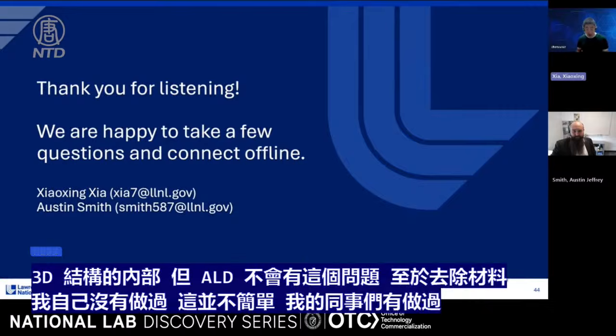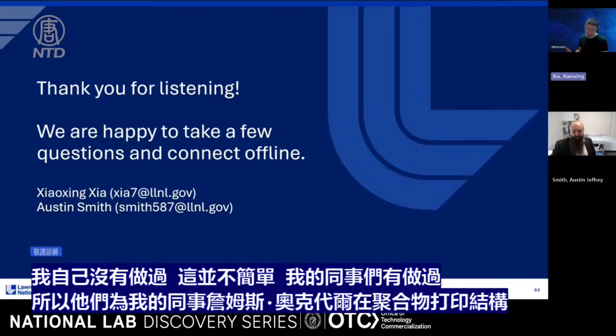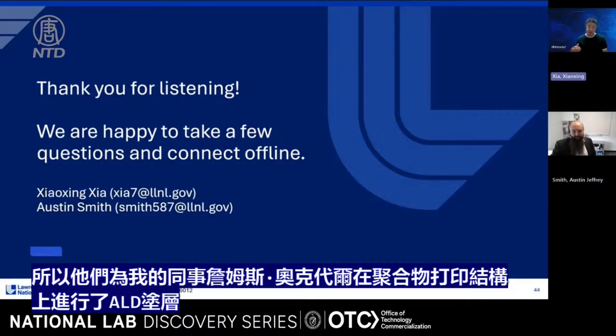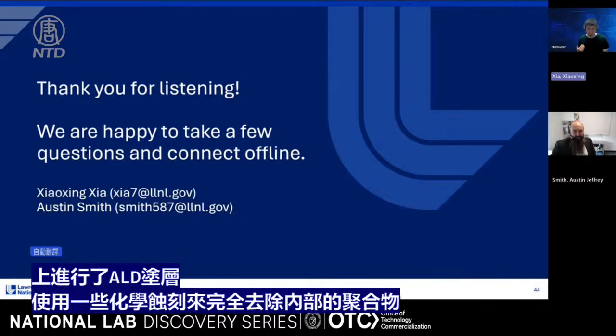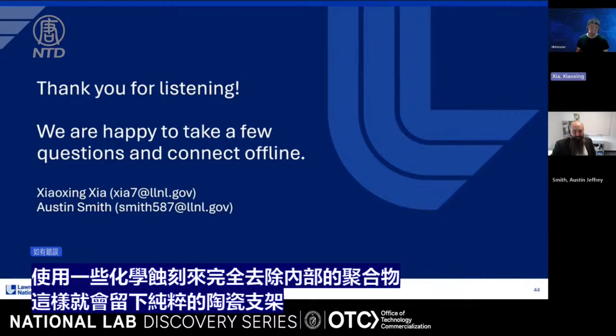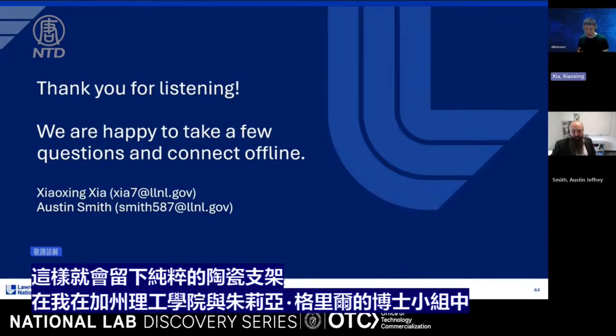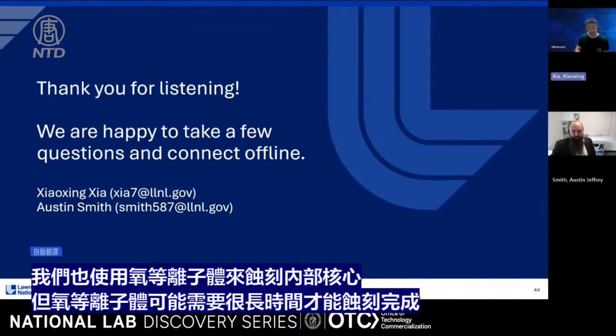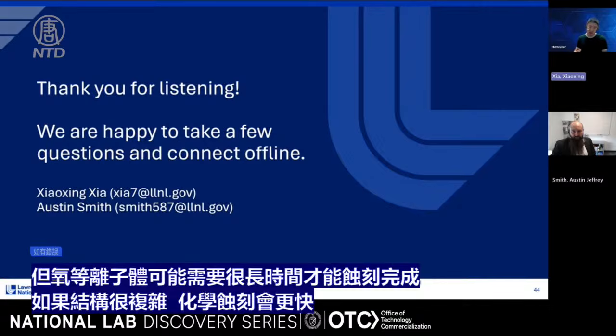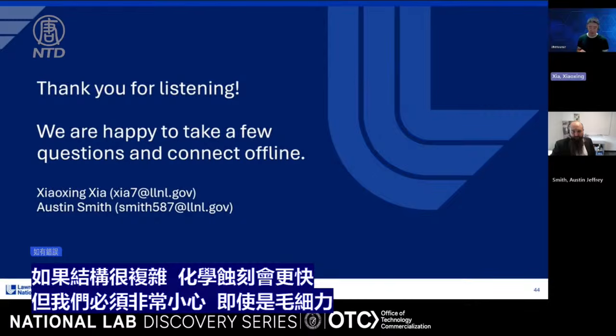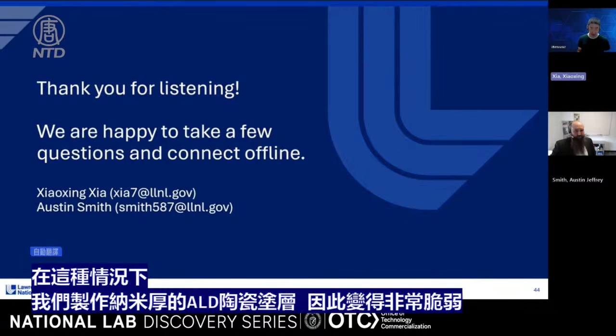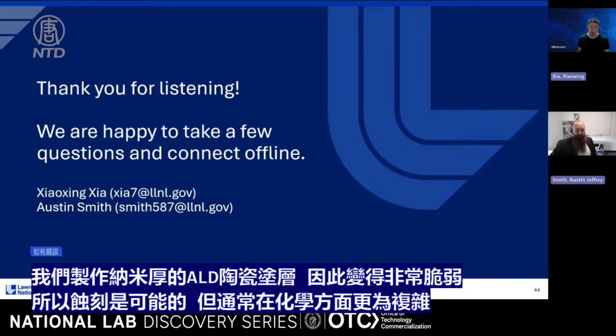To remove the material, I haven't done it myself. It's not trivial. My colleague James Ogdale has done ALD coating on polymer printed structures and then used chemical etching to fully remove the polymer on the inside, so you have a pure ceramic scaffold left. In my PhD group at Caltech with Julia Greer, we also used oxygen plasma to etch away the inner cores. But oxygen plasma takes a very long time if you have a complex structure. Chemical etching is faster, but we have to be careful about capillary forces, because we're making nanometer thick ALD ceramic coatings, so it becomes very delicate. So etching is possible, but it's more involved on the chemistry side, and it's non-trivial. It needs to be treated very carefully.